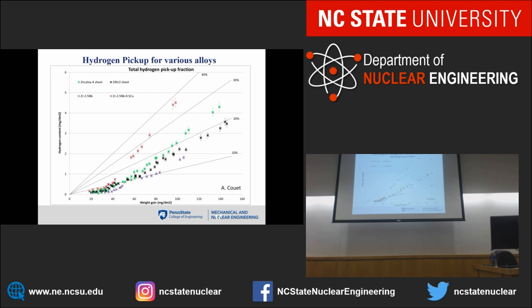The way that we have determined this is by testing. Painstaking work. You put the corrosion coupon, you test it out, measure the hydrogen, put it in again, measure it again, for every one of those. And we managed to do this by two methods. One was using a destructive method with sister samples: I have several samples, I take one out, I measure it. The other way is to use prompt gamma neutron activation analysis, which is a very sensitive method of detecting hydrogen, which we did at NIST.